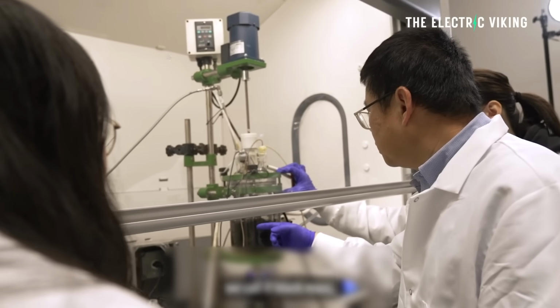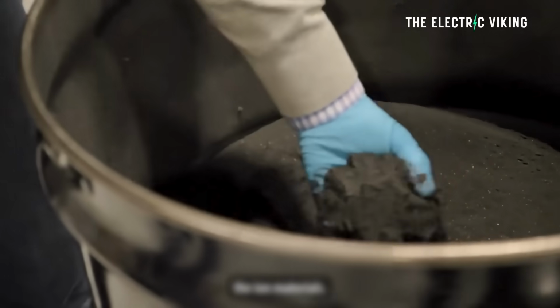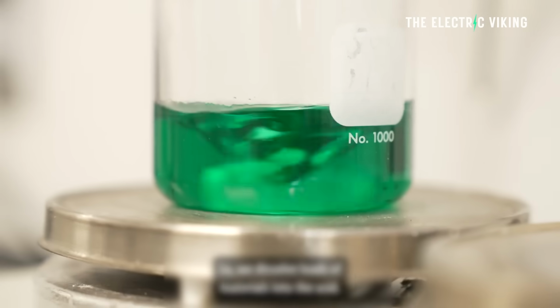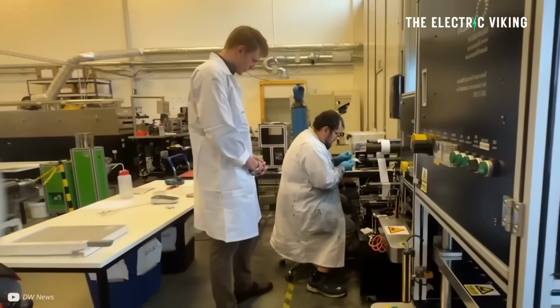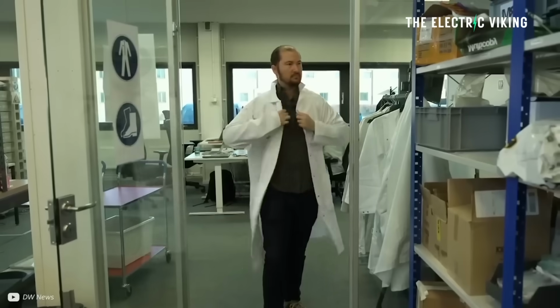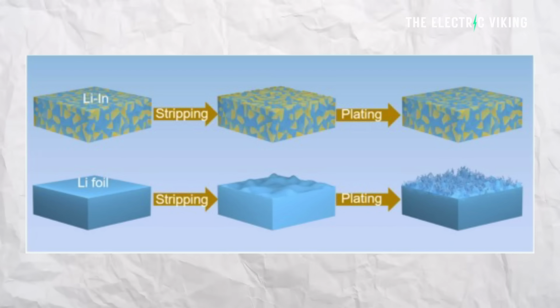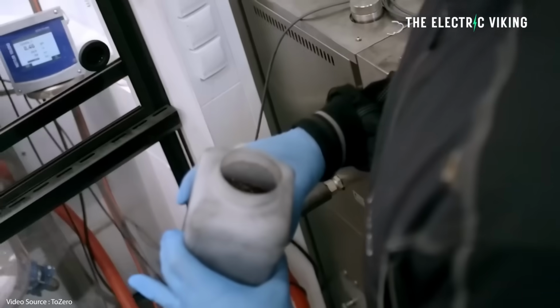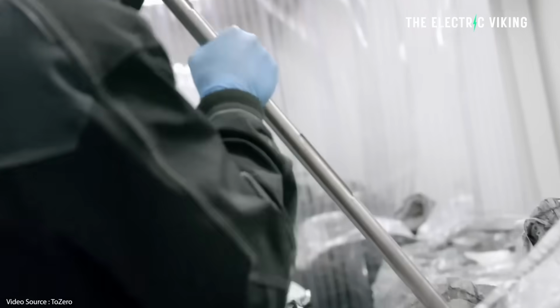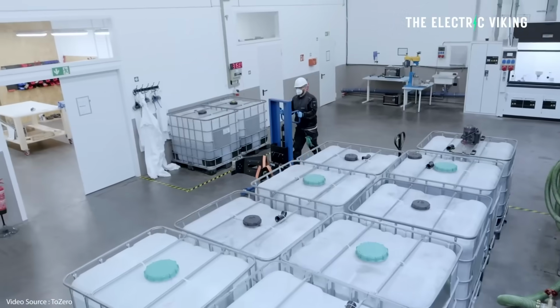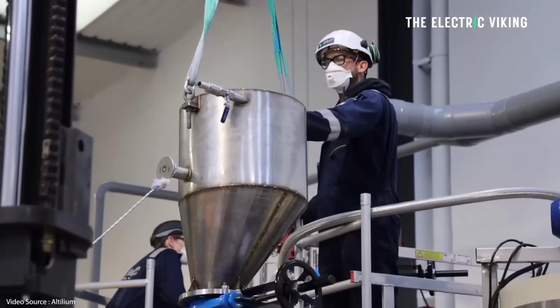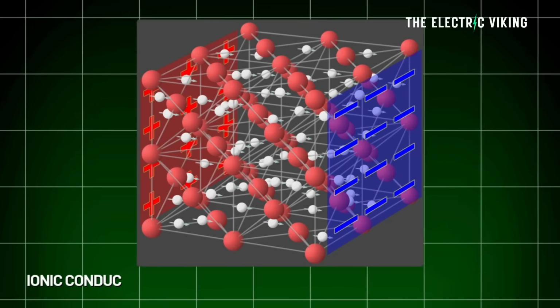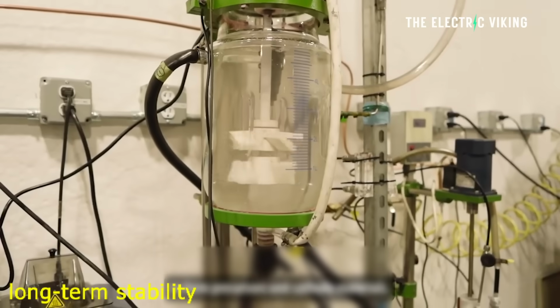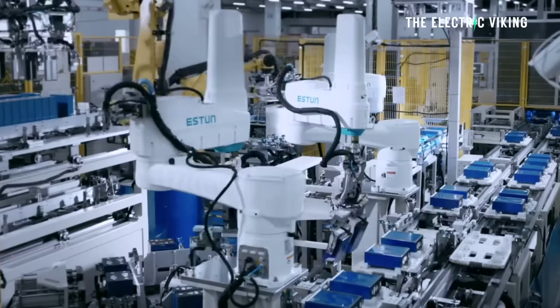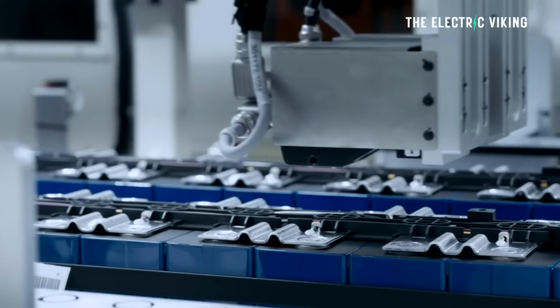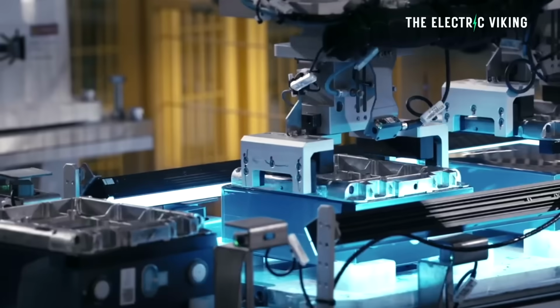The researchers solved this by doping lithium indium chloride with iron. And this modification created a material that can make direct stable contact with lithium metal anodes, eliminating the need for a costly and complex protective interlayer. Interestingly, the new material maintains excellent ionic conductivity and it shows impressive long-term stability. And that's the main issue here. Long-term stability is the biggest challenge that solid-state batteries have been facing now.